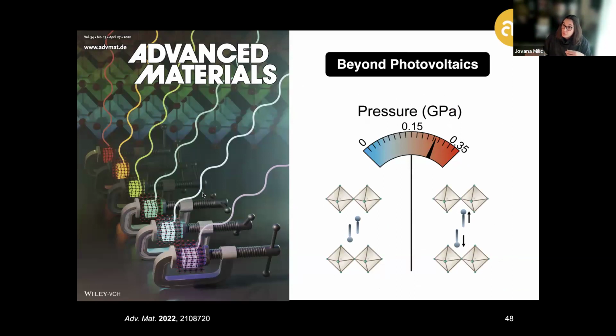That enables tailoring the optical response of these materials in response to the strain, such as in the form of external pressure, but in the pressure range that fairly corresponds to the level of strain that can be triggered by different internal structural rearrangements, which offers now the basis for relying on these systems as potentially amphidynamic scaffolds for controlling different stimuli-responsive dynamic systems, even in the solid state, and well beyond photovoltaics.